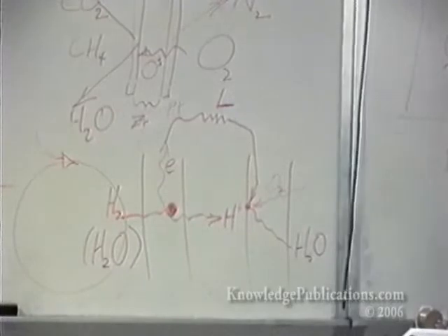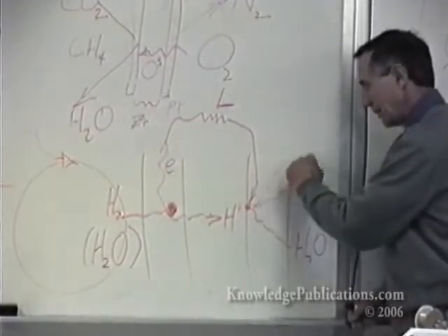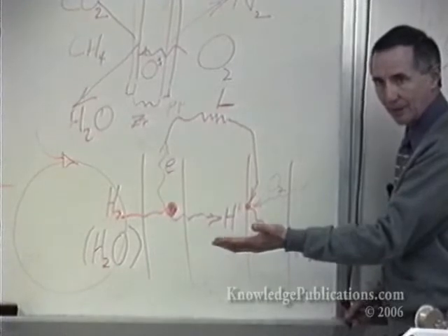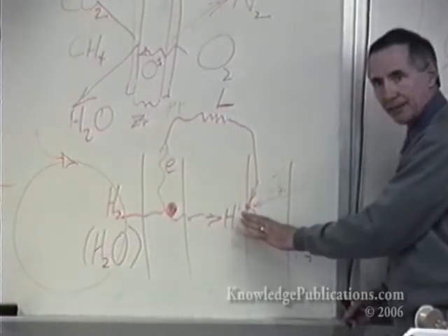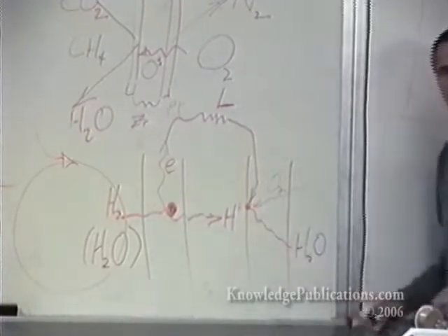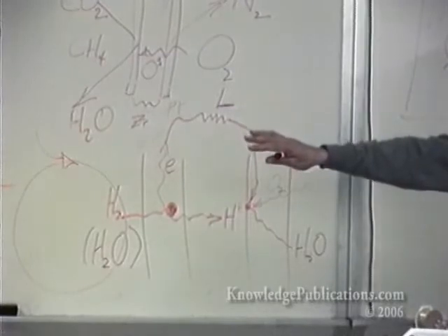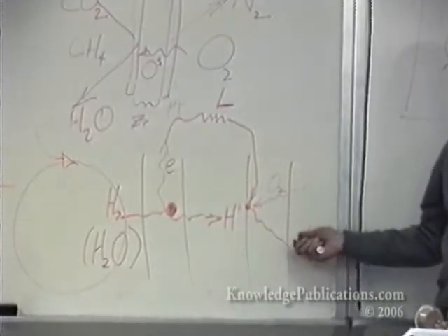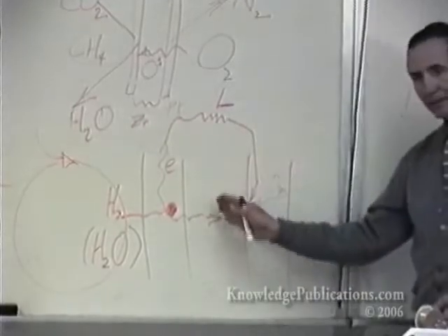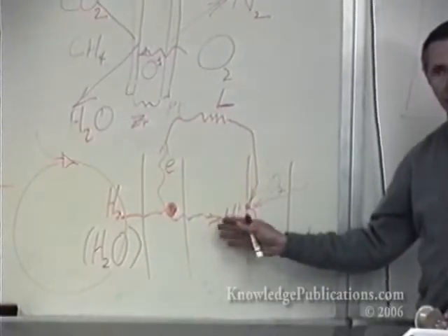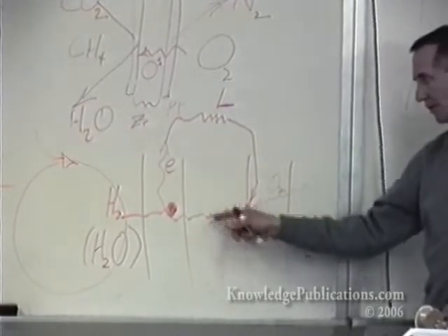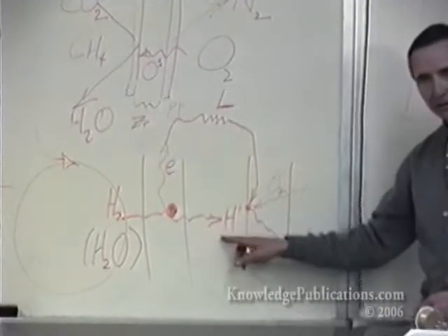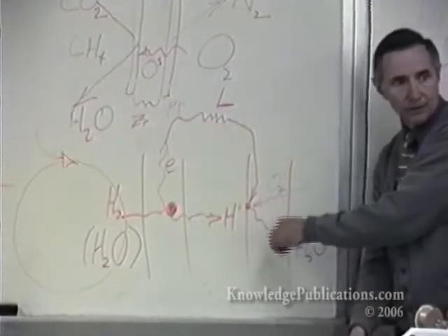You have to arrange for it to not be there. You have to arrange for it to either be removed by dehumidifying the oxygen that gets there, so it'll take up some of it, and that only works for a little while. Or you have to circulate the oxygen as the carrier to remove the water, or you have to use capillary action to divorce the water. The best selection is to have a system that is phobic of water, doesn't want water, that's always rejecting water. And this is why a Teflon-based membrane is quite helpful. It's a water rejector in that sense. Then you put places in it that are water electrolytes. And so now you have a system that is conducting these ions on the water electrolyte and divorcing water on the other side as it's producing it.